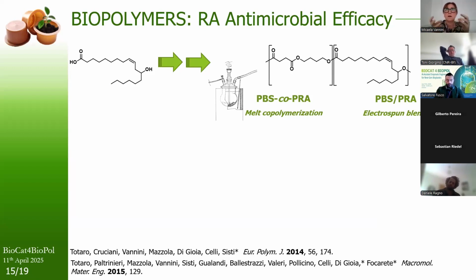to combine PRA with PBS. PBS is a biodegradable, bio-based, and semi-crystalline polymer. Therefore, we prepared copolymers through melt copolymerization and physical blends through electrospinning.